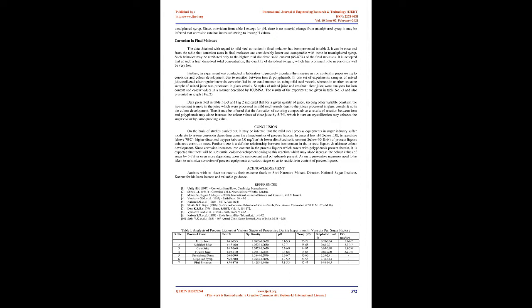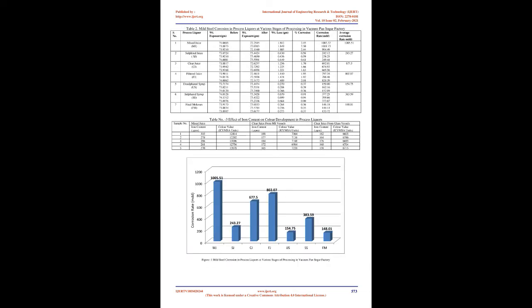Corrosion in clear juice. Apart from various other parameters, e.g. pH, dissolved oxygen content etc., it is the temperature which influences the corrosion rates. Since the temperature of clear juice remains much higher, 94 to 95°C, than any other process liquors, the mild steel corrosion was observed to be appreciable. The pH and dissolved oxygen content of the clear juice was found to be around 6.7 to 6.9 and 1.8 to 2.0 mg/liter respectively.